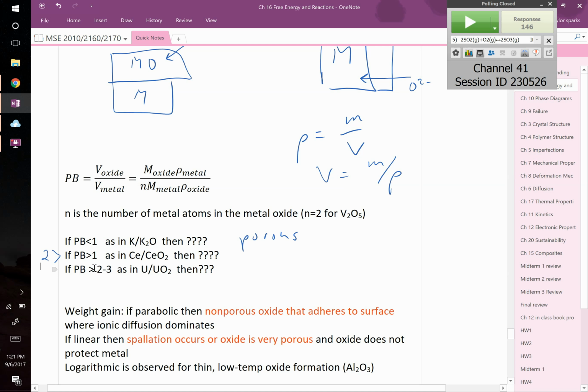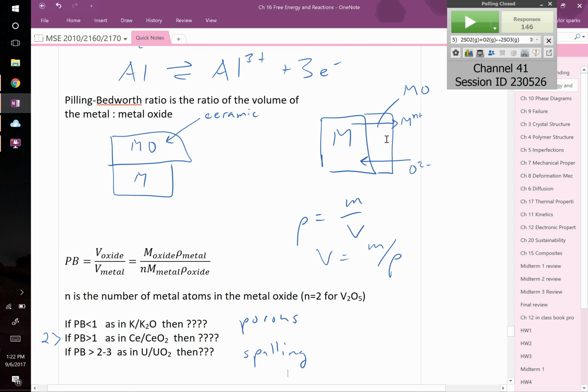But if your Pilling-Bedworth ratio is greater than 2 or 3, it's going to spall off. That basically means that the oxide is much larger than the metal, and it's just too much strain, it's going to spall off. It'll chip off and expose new metal underneath it, right? So this is where spalling occurs. So the first and the third scenario both cause continued oxidation, and the second one doesn't. And so if you were actually to plug in your Pilling-Bedworth ratio for a bunch of different metals, you'll realize why some things corrode easily and some things, even though thermodynamically they look like they want to corrode, they don't, because they're kinetically limited, because you just can't get ions to transport through this layer.